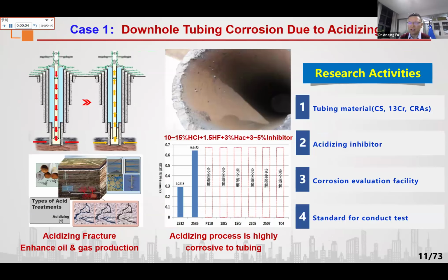The first case is for the downhole system. The acid fracture is widely used for enhanced oil and gas recovery or production, where it can cause severe corrosion to tubing as well as casing. Since the acid solution is very acidic, it will cause very severe corrosion in several hours or in several days.